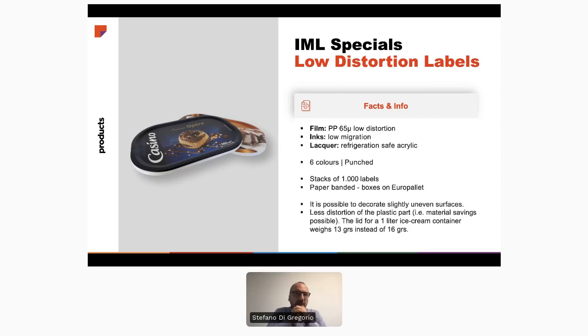Now, with these low distortion labels, we use softer and lighter material, which allows for decreasing the part's weight, so decreasing the plastic material we are putting into the part, by having less influence on the warpage. Like you see here on the last sentence of the slide, this is a lid for a 1 liter ice cream container, which weighs 13 grams instead of 16 grams as before. Before, 16 grams was the limit, because otherwise we would have warpage of the plastic part. But with this film, we were able to design a lid which is thinner and lighter.